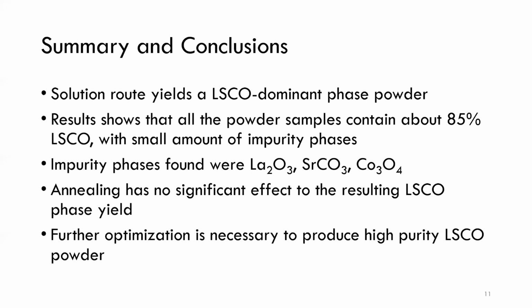As a summary, we present a simple route to prepare strontium-doped lanthanum cobaltites using an aqueous precursor solution. Our result shows that all the powder samples contain about 85% LSCO with a small amount of impurity phases. Impurity phases that are found were lanthanum oxide, strontium carbonate, and cobalt oxide. Annealing has no significant effect on the resulting LSCO phase yield. Further optimization is necessary to produce high purity, which is greater than 95% LSCO powder.